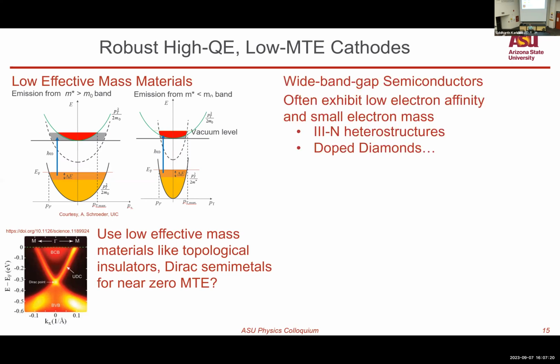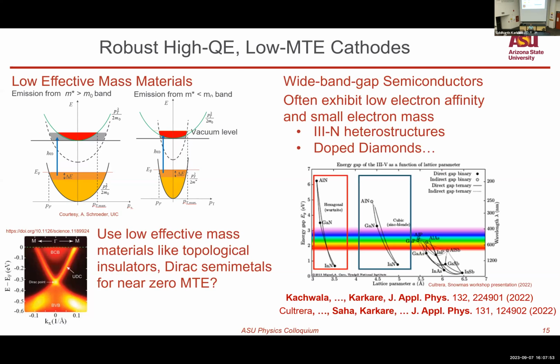Another class of materials are wide bandgap semiconductors. They often have very large bandgaps and also hence exhibit low electron affinity and a small electron mass. III-nitride heterostructures can be quite interesting, something which we are exploring. There's also doped diamonds, which we'll be working on with Bob very soon. These materials typically emit electrons in the UV. Their band gaps are in the UV range, but you can develop heterostructures and alloys of these materials which have band gaps in the visible range and could possibly emit electrons in blue light. And those are some of the things that we are working on towards making robust high QE, low MTE cathodes.